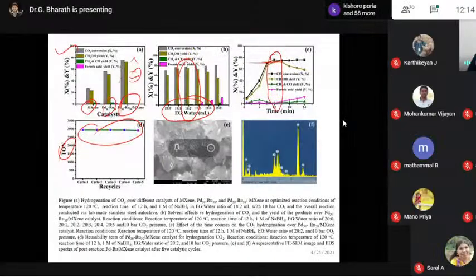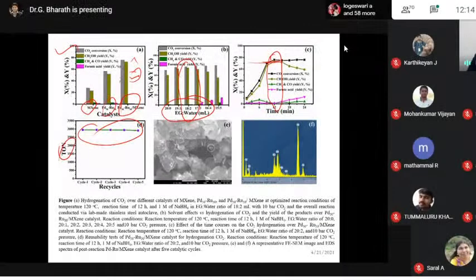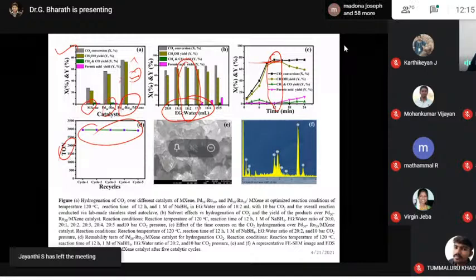We also found the optimum time. At 12 hours, we reach almost 70% CH3OH yield and 75% CO2 conversion. And this is the turnover number. We are obtaining the maximum turnover number per hour. So this is our complete research, and we successfully converted CO2 into fuel, especially methanol. But we need a high-pressure reactor for this reaction, and temperature and time, almost 12 hours. So this has some disadvantages.